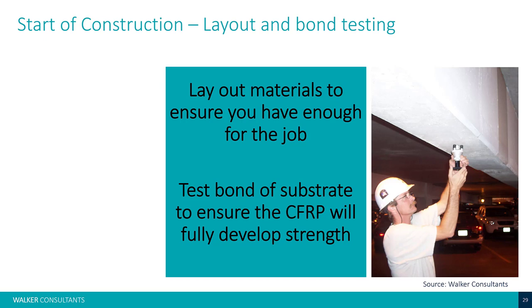Also, you can see in the photo on the right, here we're looking at a painted beam. We've talked about this before in the presentation, that any coatings or anything like that could be a bond inhibitor. So we actually want to get out there and glue a puck onto the surface. We want to test that actual coating to see if it's got enough bond to actually transfer the load between the carbon fiber product and the base concrete. In this case, and I'll show this later on in our demonstration, this particular test failed. So we had to remove all the paint or whatever coating it was from the beam.